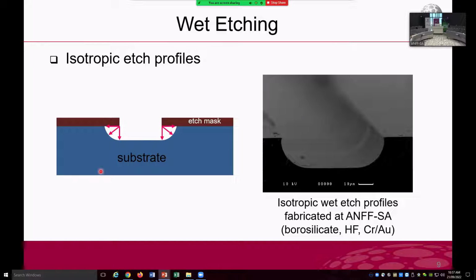And this shows the wet etching profile. This SEM image shows the isotropic wet etch profiles formed on a borosilicate substrate by using hydrofluoric acid. This is an isotropic etchant, and then chromium gold as the etch mask layer.